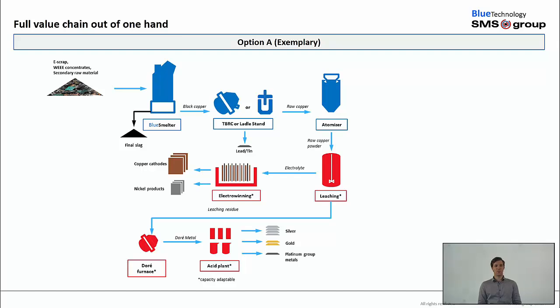In option A, we're focusing on optimizing this raw copper. That means we generate a very fine powder which is usable for a leaching process. In this leaching process, copper and nickel go into solution and are further transferred to an electrowinning process, where we generate products such as copper cathodes and a nickel product. In this leaching process, the more noble metals like gold and silver do not go into solution and are collected in a sludge. This sludge is then transferred into the precious metals plant, where we separate all these metals from each other and transfer them into high-grade products.